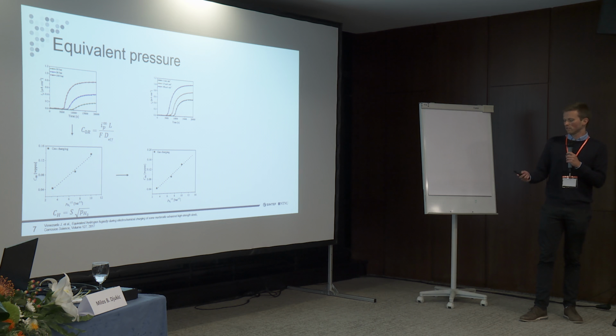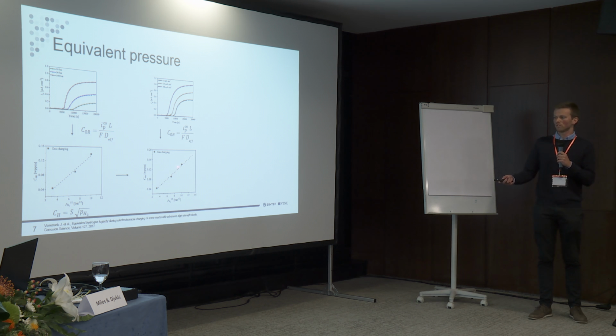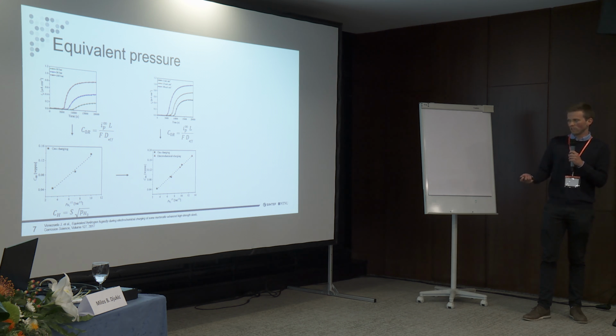So then we use this plot and extrapolate this line, and we take the results we have from electrochemical permeation. We calculate the subsurface hydrogen concentration and superimpose the results onto this line. So you can see the points here. For example, this first point corresponds to the -1 milliamp per centimeter squared charging. And then we can take this point and read off the equivalent charging pressure, which would be 45 bars. So it would mean that if you want to represent the same hydrogen concentration with electrochemical charging as 45 bars would give you, you could charge at -1 milliamp per centimeter squared.